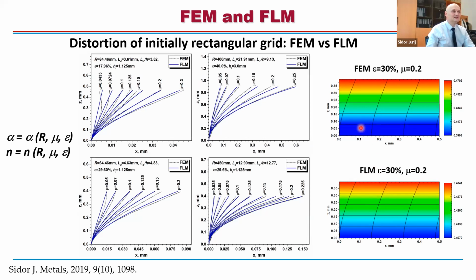We did this exercise for many roll gap geometries, not only this one, what you can see here for different thickness reductions, different roll diameters. And as you can see, we could reproduce basically these lines you can see here. We could nicely reproduce almost all finite element results. So once you have knowledge of the deformation, the amount of deformation, how it is distributed inside the material, you can move to the next stage.